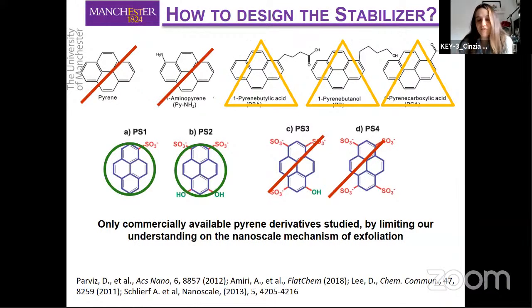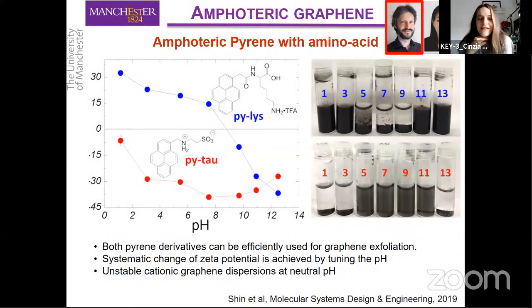Because of that, we decided to work together with the organic chemist in my department and start synthesizing different pyrene derivatives from scratch, in order to produce graphene dispersions with specific surface charge and chemistry. For example, we investigated the use of amphoteric pyrene derivatives to change the charge of our dispersions. The exfoliation is done in neutral conditions, and after that we change the pH in order to change the surface charge.